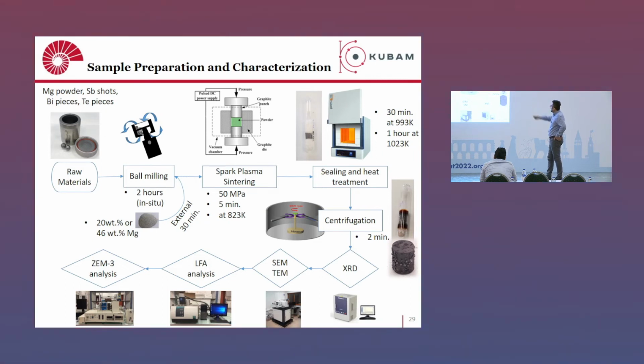You do sintering with spark plasma sintering at certain conditions to make this bulk material. And then we seal this bulk material in a quartz ampoule under protective atmosphere, because if you take this and put it in an oven, it will be oxidized. To avoid that, we just put it in a quartz tube and then put this in an oven. Then we did a quick centrifugation, and you can see that the magnesium in the molten state just comes out from the bulk piece, and you can clean this and investigate the microstructure. Of course, the first thing we do is XRD for phase analysis, TEM and SEM for the microstructure analysis, LFA for thermal conductivity, and ZEM3 for the electronic transport characterization.